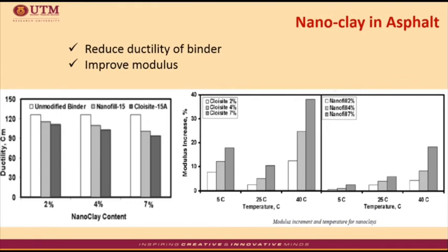Next are the results of the previous study in terms of ductility and modulus. From the results, it shows that the addition of nano clay seems to reduce the ductility of the asphalt binder and improve the modulus of the binder with the increase in nano clay content and temperature of the testing, compared to the conventional or unmodified binder.